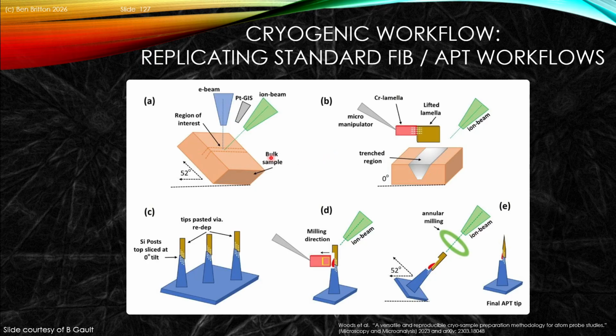What became quite apparent is that effectively the hydrides that are presented, you actually get significant hydride formation due to the influx of hydrogen in the FIB prep. And so this motivates effectively the use of cryogenic methods that can reduce that approach. Cryogenic methods in this case are relatively similar to what was done beforehand, except the whole system is kept cold to enable this to work.